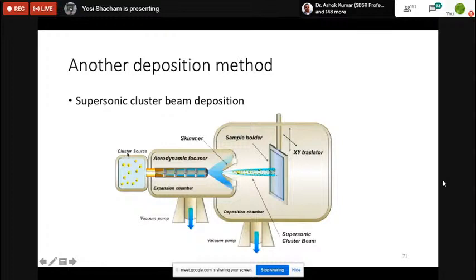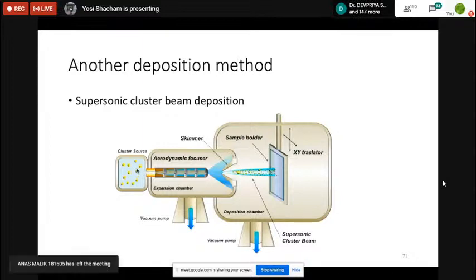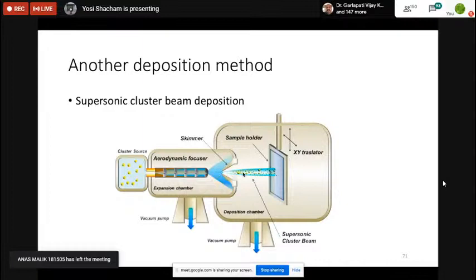And the idea is to take a source which is called a cluster source, and you are generating nanoparticles of metals. And these nanoparticles can be 1 or 2 nanometers in size. You accelerate the nanoparticles, and you shoot them into your PDMS. Remember, PDMS is your flexible substrate, and you want to make the flexible device on the substrate. So you put gold into it.